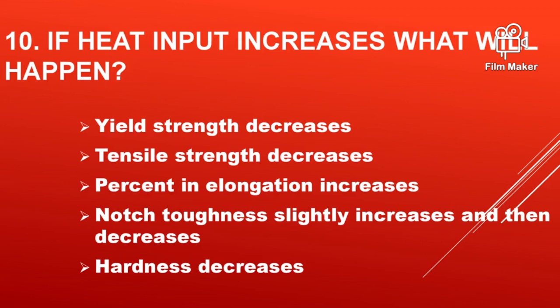If heat input increases, what will happen? Yield strength decreases, tensile strength decreases, percentage elongation increases, notch toughness slightly increases and then decreases, and hardness decreases.